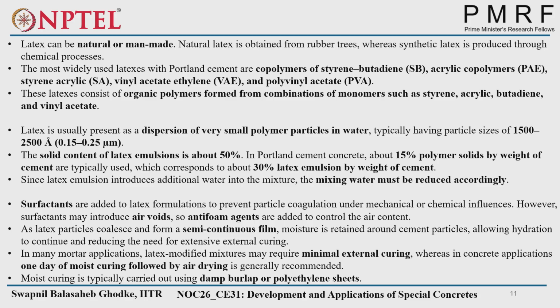As latex particles coalesce and form a semi-continuous film, moisture is retained around the cement particles, allowing hydration to continue and reducing the need for extensive external curing. As we saw in the previous image, the latex forms a film around the unhydrated or hydrated cement or the inert material, whatever is available, that is aggregate or any other. That latex film has a certain amount of water, and we can use that water for further hydration processes also.